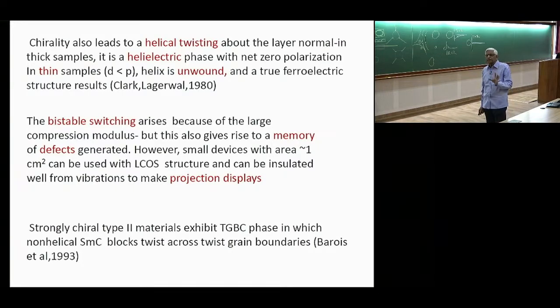The reason is very simple. Smectic liquid crystals have memory, not just for what you have done, reoriented, but for any defect that is in. And if you get a large enough device, there will always be defects. Nematic knows how to heal itself because of the strong anchoring at the surface. The Smectic doesn't know how to heal itself. So you cannot make large devices.